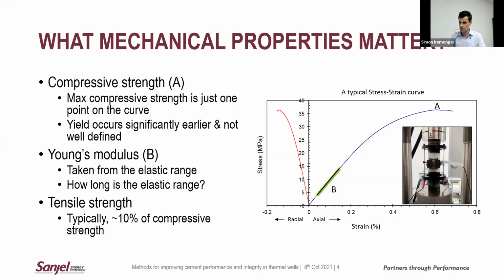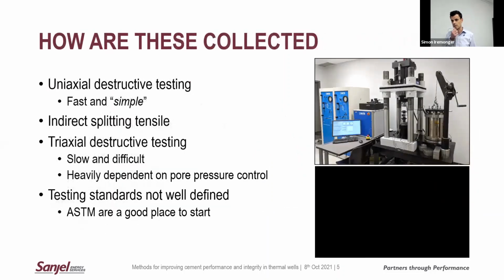We like to talk about Young's modulus, and that's your elastic range. That's where, before yield. And so certainly you want to typically have a nice low Young's modulus. But ideally also extend that out so that you're maximizing your elastic range and minimizing that plastic deformation as well as you can. And one of the big downsides of cement really is that typically its tensile strength is unfortunately quite low, generally in and around 10% of your ultimate compressive strength. So certainly that's a challenge, and you can quite often see a lot of tensile failures due to high hoop stress because you've got low tensile strength in your cement. So that's certainly been something that we've focused on.